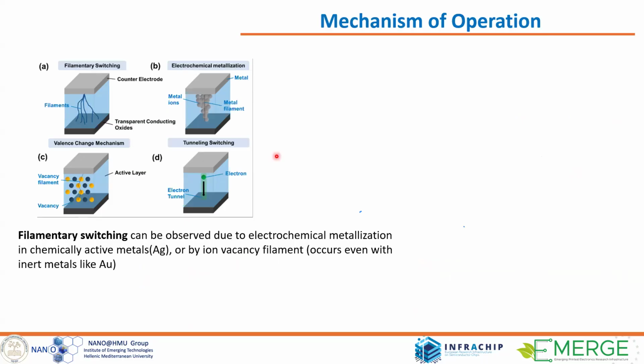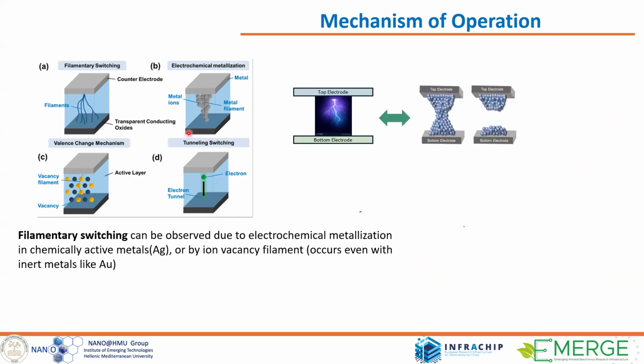About the mechanism, I told you some details previously. We have two main types, at least for the perovskite community. One is the filamentary switching. As I told you, when we apply a high electric field, we have ion and carrier migration, mainly ions in perovskites, and we have some vacancies that are charged, and these vacancies are conductive. So the vacancies in perovskite-based systems, and maybe in some oxides, are the source of the filament formation.